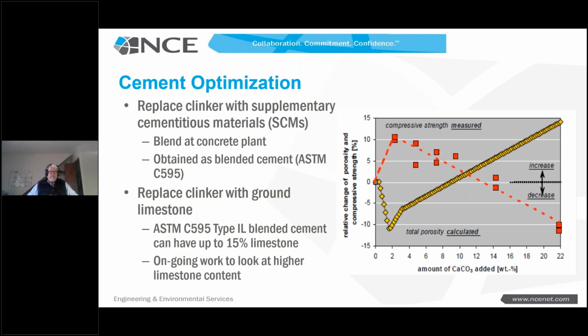A second thing that we can replace with is limestone. In the US now, with ASTM C595 Type 1L cement, which many of you are probably seeing in your markets if you're in the US, basically you can intergrind realistically 12%. I think some are pushing it up to now 13, 13.5% interground limestone. It works very well together with an SCM, and we'll talk about that. So we can start to reduce the clinker content of that cement, and that's the way to really drop that clinker factor, or the kilograms of CO2 per kilogram of cement.